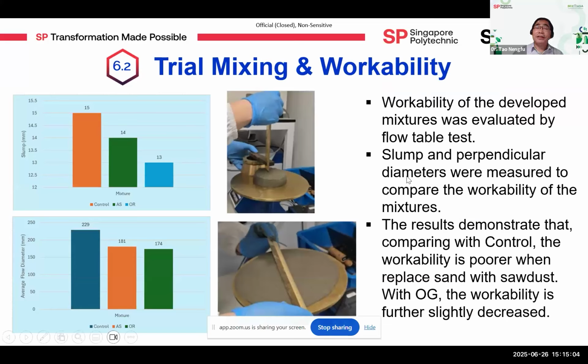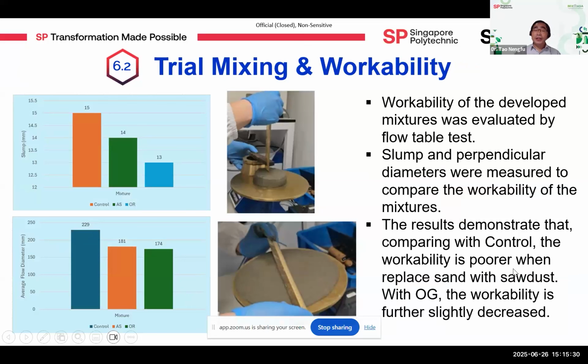The slump and the perpendicular diameter were measured to compare the workability of the mixture. The results shown here in the bar chart demonstrate that, compared with the standard control, the workability is poorer when replacing sand with sawdust. With OG, the workability is further slightly decreased.